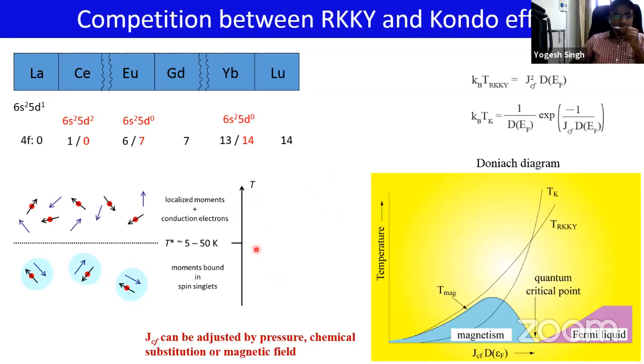So the local moments are surrounded by a cloud of conduction electrons, which are oppositely polarized. What also happens is that because there are local moments in a conduction sea, they will interact indirectly via the RKKY interaction. So the RKKY wants to order the moments, and the Kondo effect wants to quench the moments. And therefore, there is a competition between these two effects.